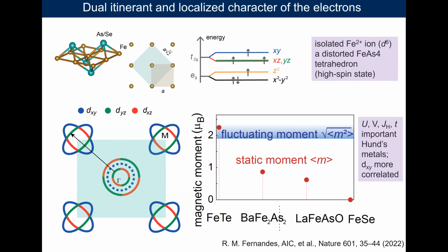The systems are strongly correlated, and the way the magnetism behaves is very important and not easy to understand because we are dealing with itinerant systems. So these magnetic moments are likely to fluctuate a lot. And probably that's also the reason why iron selenide never orders. There's been a suggestion that it could be a competition between different types of magnetic order, which are trying to destabilize each other. But even if it doesn't order, we should assume that those magnetic spins are still there, and some of them are likely to be important for scattering. And another thing: when we extract various parameters about these materials, often the dxy orbital character of these bands is also more correlated. So we have this differentiation in correlation depending on the orbital characters of the bands.